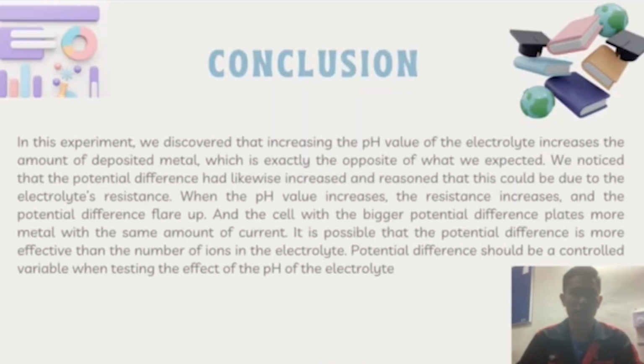This is the conclusion. In this experiment, we discovered that increasing the pH value of the electrolyte increased the amount of deposited metal, which is exactly the opposite of what we expected. We noticed that the potential difference had likewise increased, and reasoned that this could be due to the electrolyte's resistance. When the pH value increased, the resistance increased and the potential difference went up. And the cell with the bigger potential difference plates more metal with the same amount of current. It is possible that the potential difference is more effective than the number of ions in the electrolyte.